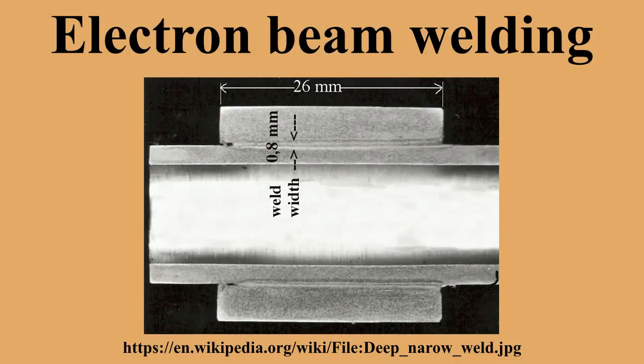The volume density of power in the small volume in which the kinetic energy of the electrons is transformed into heat can reach values of the order of 10^5 to 10^7 W per cubic millimeter. Consequently, the temperature in this volume increases extremely rapidly, by 10^8 to 10^9 K per second. The effect of the electron beam under such circumstances depends on several conditions, first of all on the physical properties of the material. Any material can be melted, or even evaporated, in a very short time. Depending on conditions, the intensity of evaporation may vary from negligible to essential. At lower values of surface power density, the loss of material by evaporation is negligible for most metals, which is favorable for welding.